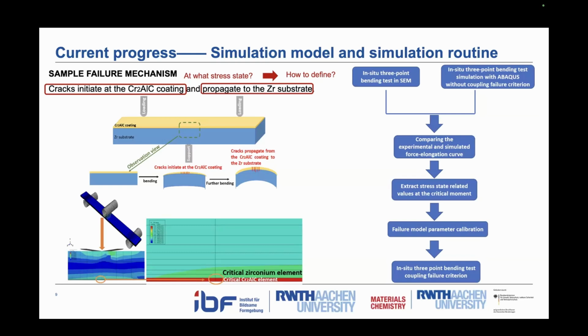And we extract the stress-related parameters at the critical moments, including the equivalent plastic strain, the maximum principal stress, stress triaxiality, and load angle parameter. And we establish a failure criterion, and we calibrated the corresponding parameters. After we finish that, we run another round of numerical simulations to validate our models and also our parameter calibration.